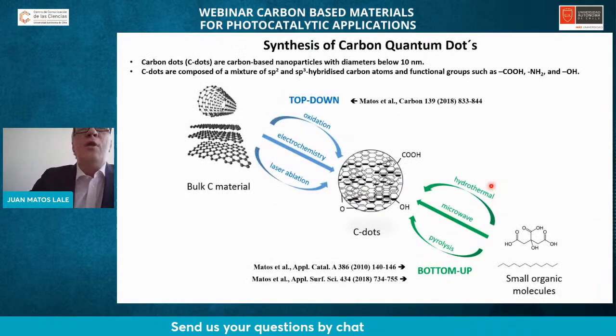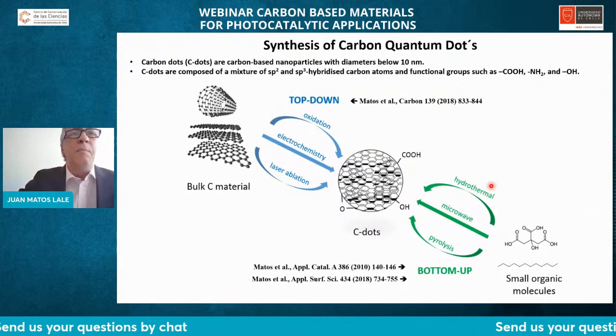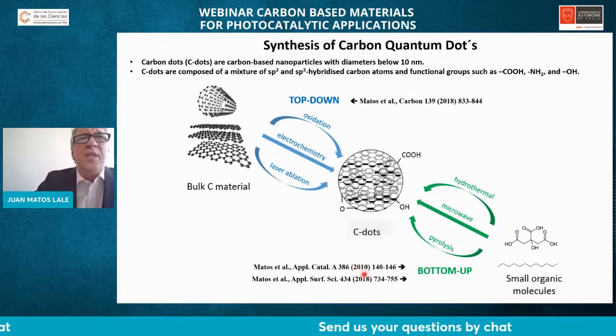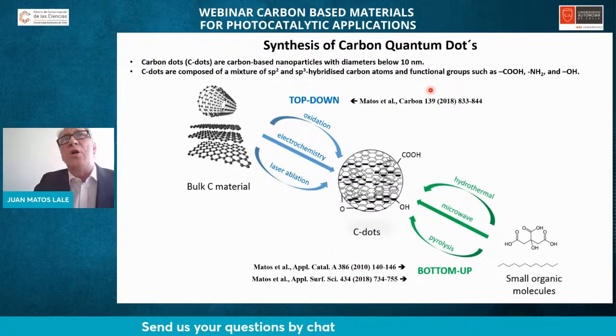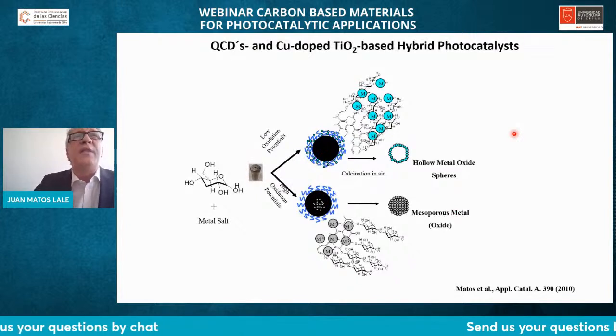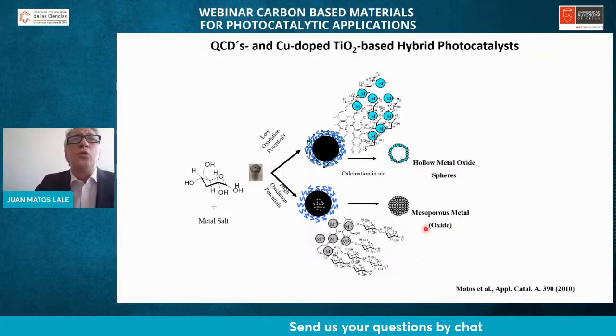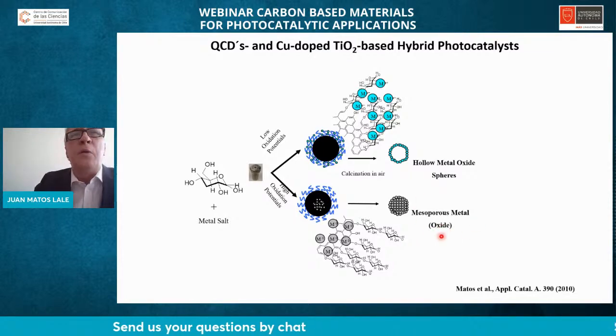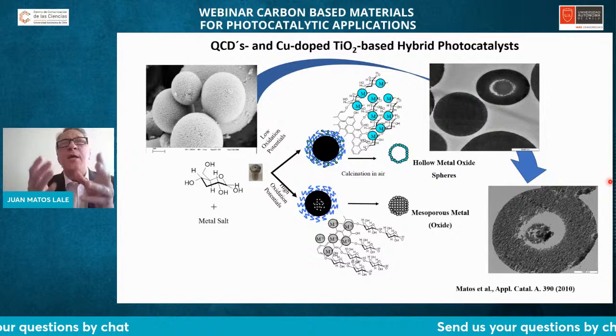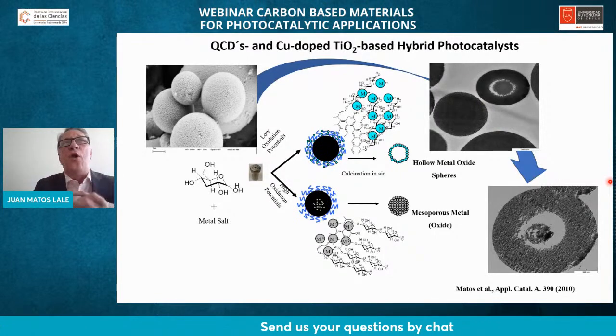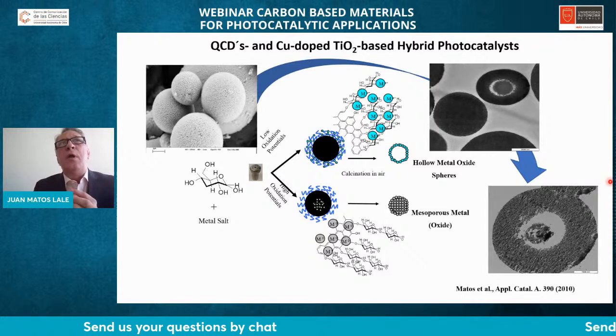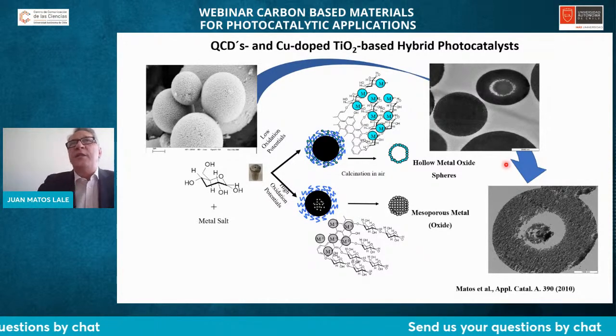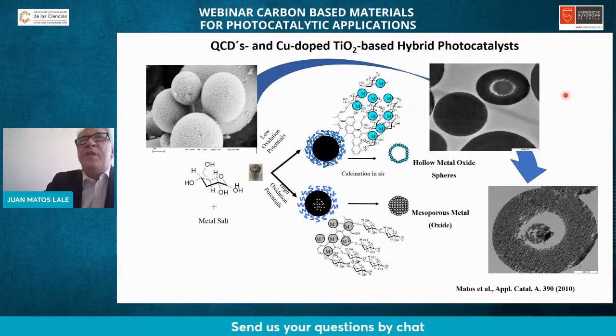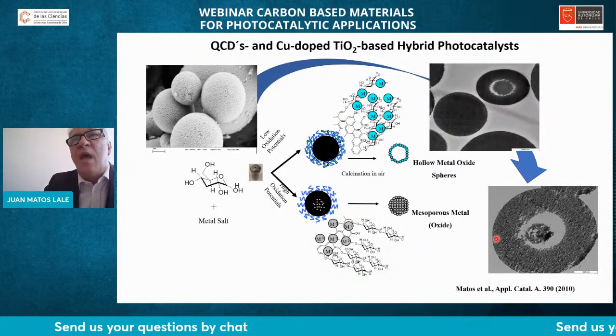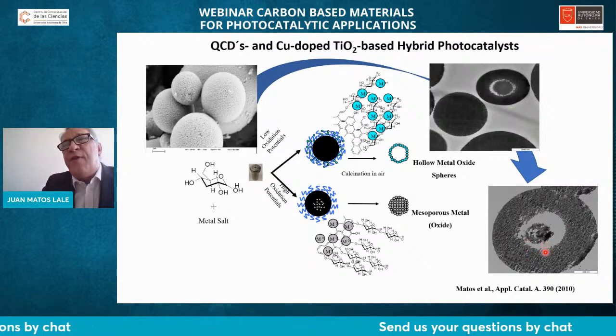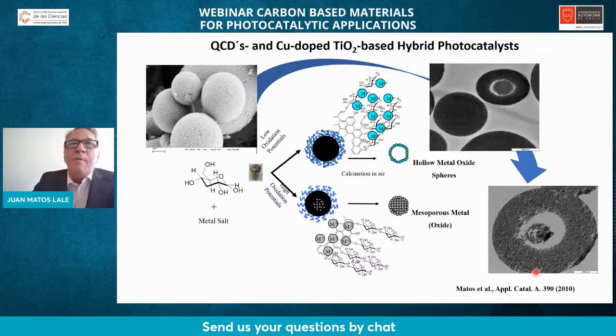So in this result, we go back to very old results that we published more than 10 years ago on the production of carbon quantum dots. And when we dealt with that, we were able to control not only the mesoporosity, but also the empty inner spaces of the spherical forms of carbon quantum dot and copper doped titanium-based hybrid photocatalyst. This was published 12 years ago for the case only in the presence of titanium dioxide. We were able to control the inner space of the sphere, which introduced an increase in the light harvesting efficiency.